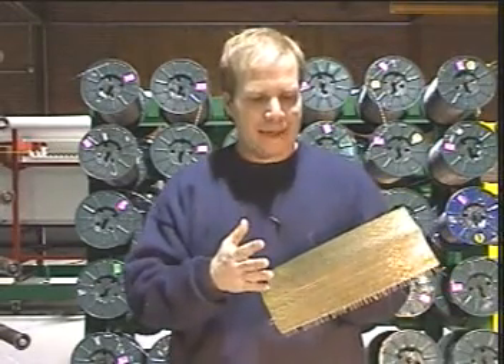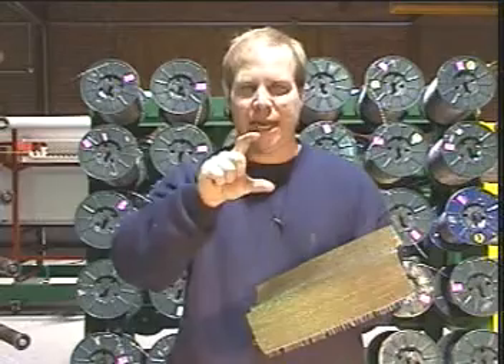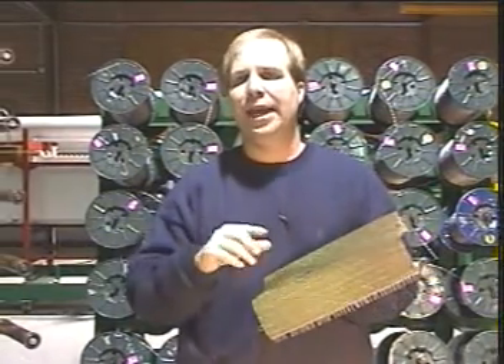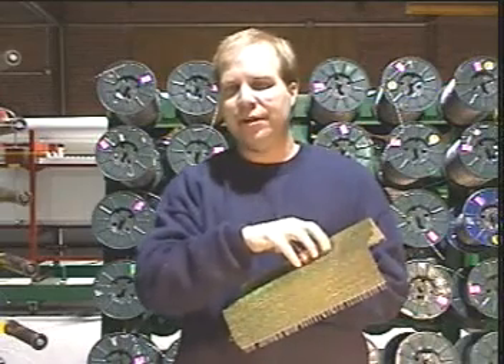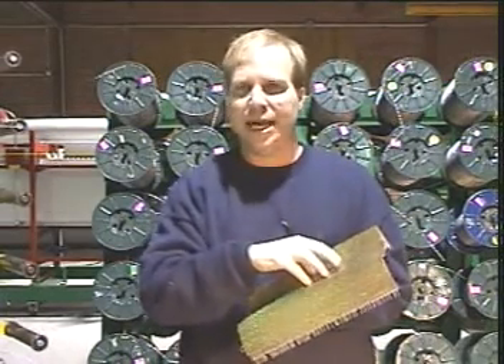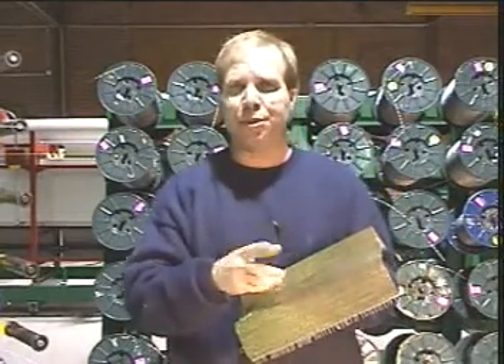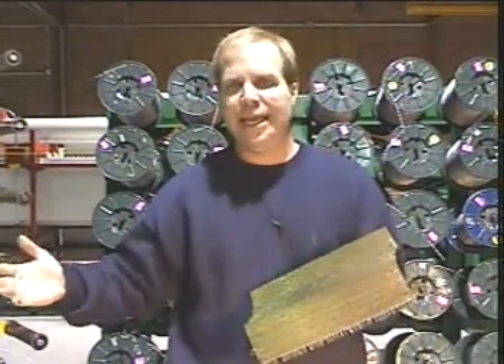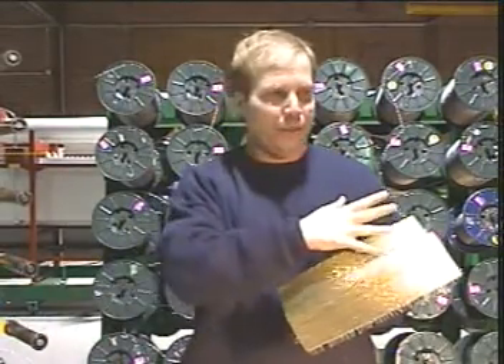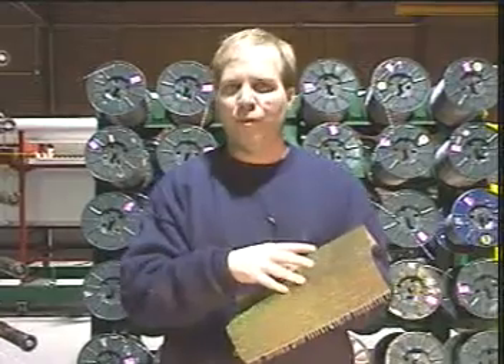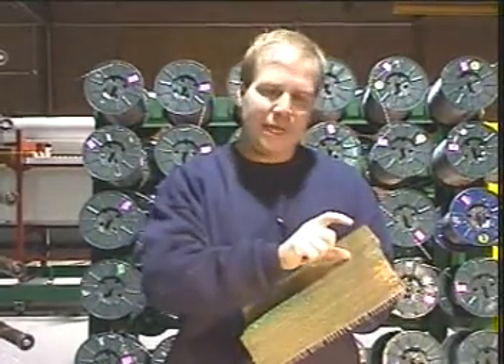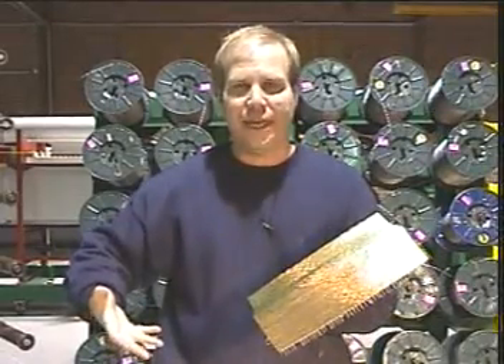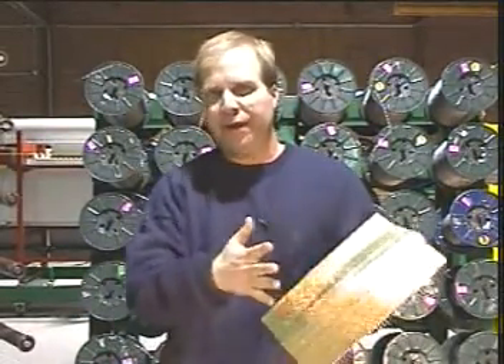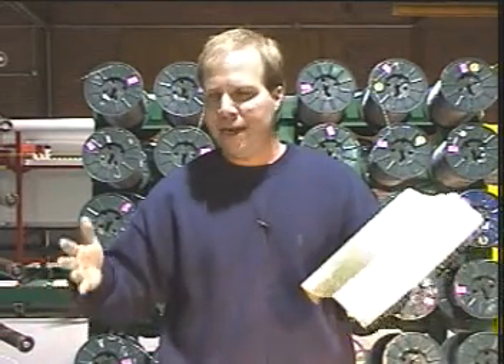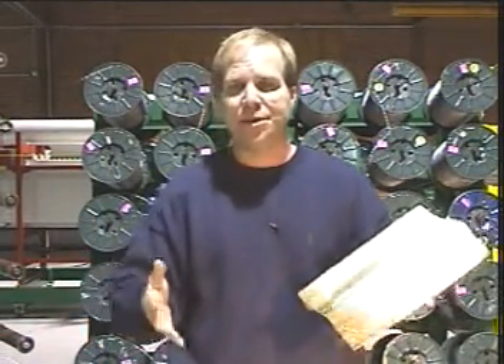Last, for the wind blade builders, guys building tapered parts, what's so dramatic about Hardwire is in tapered parts where you have thick sections followed by thin sections down further in the blade, you can use chemistries that are very, very hot in Hardwire that you couldn't get away with in glass. In glass, you usually get a peak exotherm or a runaway exotherm in the thick section, while very little of that heat or energy is transferred to the thin section. So part of the part's too hot, part of the part's too cold. With Hardwire, the beauty is it's so thermally conductive that if the thick section is heating up, the wires act to transfer that heat down to the thinner section in the mold, and you end up with a very, very even temperature profile, which results in a nice even cure, lower thermal stresses, and again, faster cycle time.